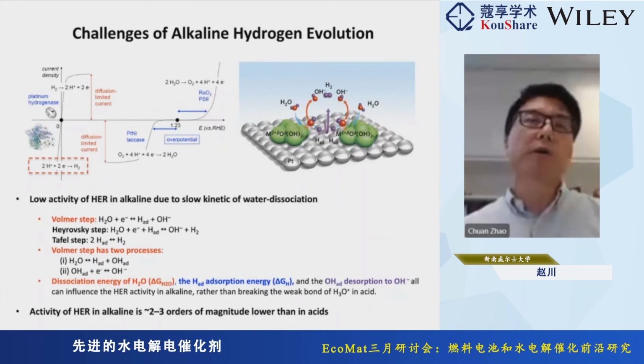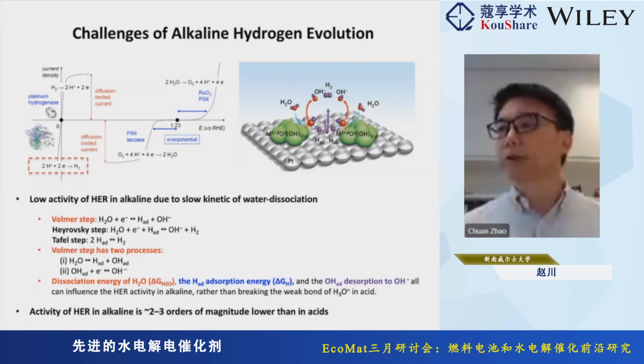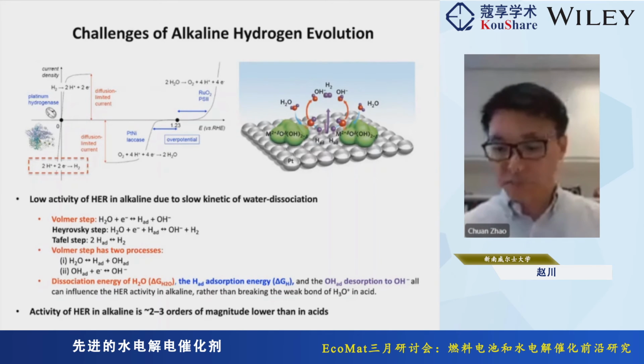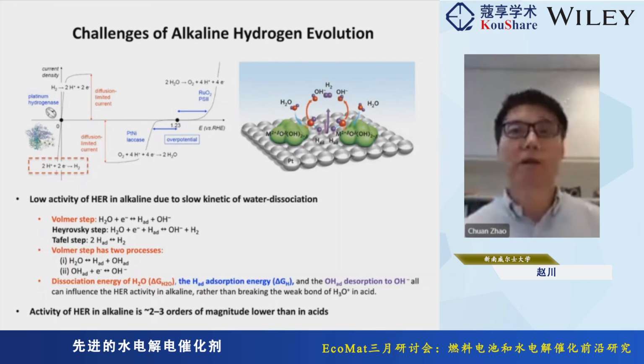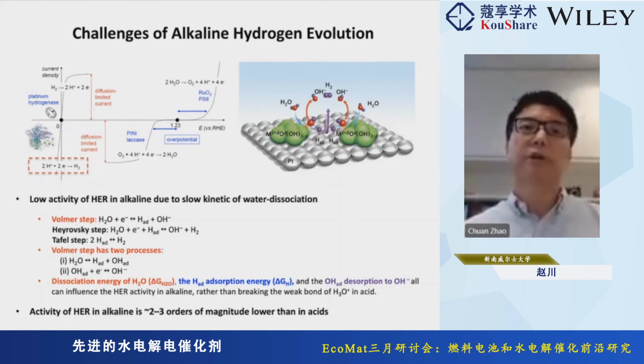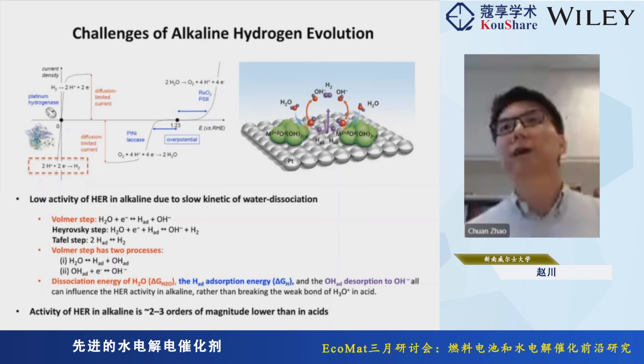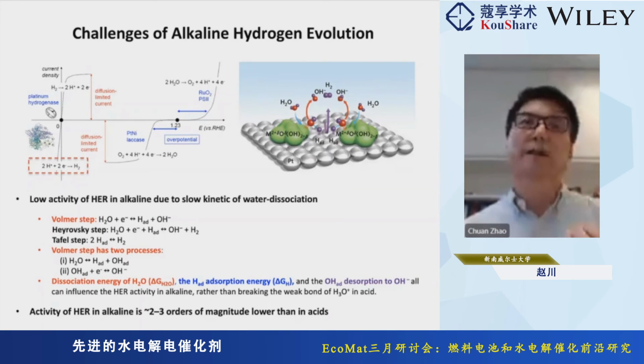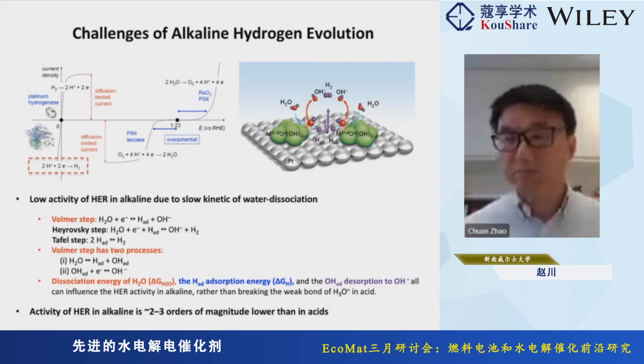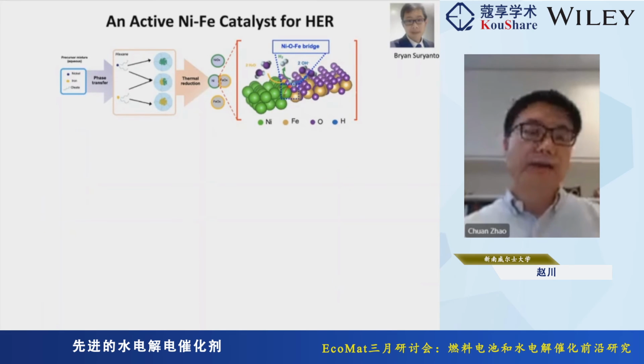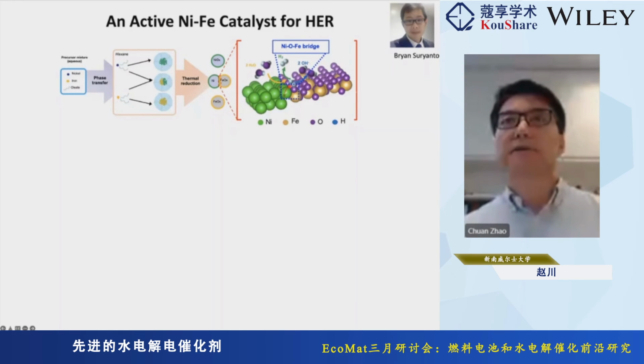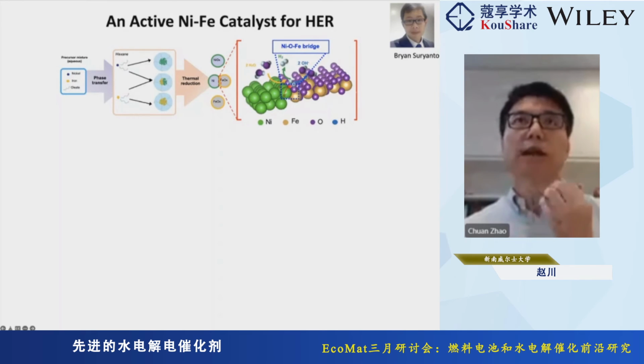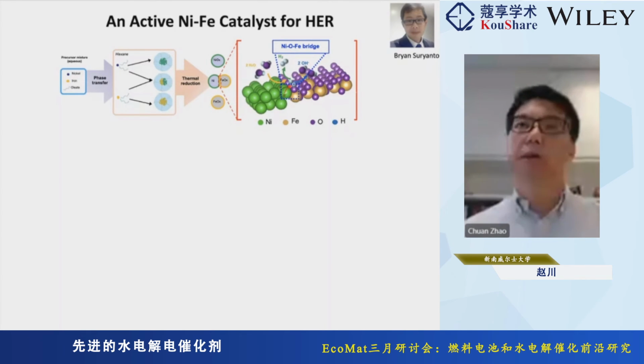Okay, I've talked about the OER. I want to quickly talk about the HER as well, particularly the alkaline HER. In alkaline HER, there's an additional step involved, which is water dissociation, which involves more intermediates competing for the active sites. Therefore, the activity of the HER in alkaline is a lot slower than in acid. To solve that problem, we need active catalysts with multiple active sites or active sites with multi-functionality. Again, nickel iron is usually considered a good OER catalyst, but not usually an HER catalyst. So in this study, we show a nickel iron catalyst which is highly active for OER and for HER as well.